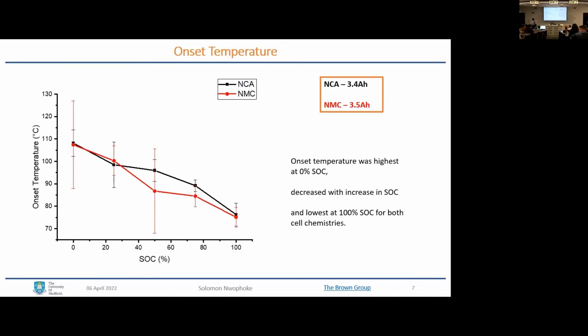And the same thing happened for the NCA, which is the black plot. You can observe here that the onset of NMC is mostly slightly lower than that of NCA, except for 0.25 state of charge. Probably that's because the capacity of the battery is a little bit higher. It has more energy stored inside of it at the point of the test.